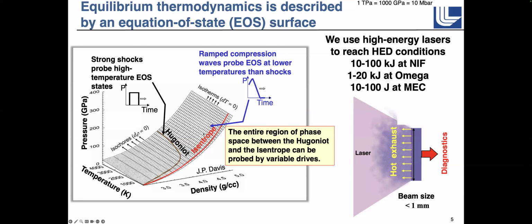And in fact, if you ramp compress something and it has no strength or other dissipative mechanisms, you can essentially follow an isentrope. And so in a liquid, for example, following an isentrope is relatively easy. In a solid, you've got strength, and so you get plastic work heating, and you're at a little bit higher pressure. But using dynamic compression, if we can use both a shock and then a ramp, we can actually access this entire temperature, density, pressure region between the Hugoniot and the isentrope. We can never get below the isentrope because there's not enough time to pull energy out of the system.